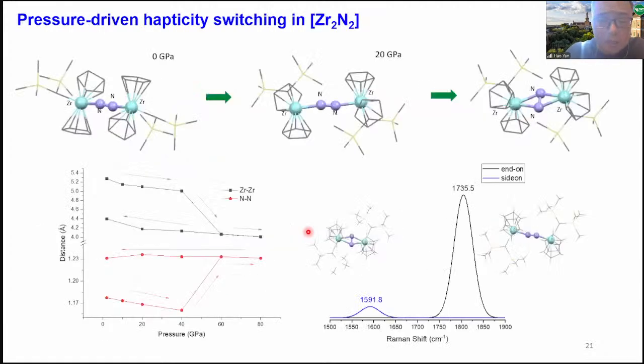The model compound we identified by computational screening was reported by Paul Chirik back in 2014, and it features a dizirconium dinitrogen structure. The zirconium is ligated with Cp ligands and alkyl ligands, and the nitrogen binds in a so-called end-on conformation - one nitrogen binds to one zirconium, the other nitrogen binds to the other.